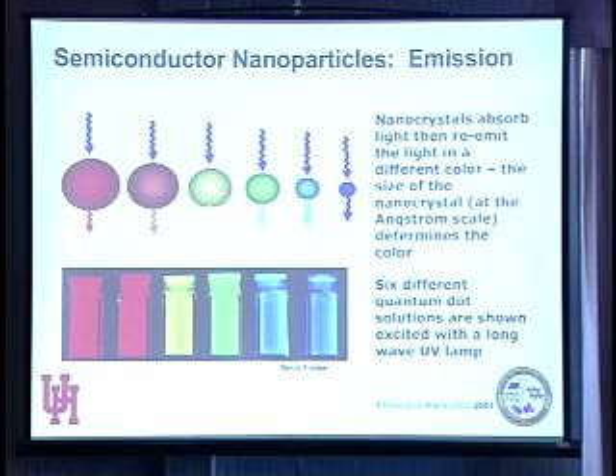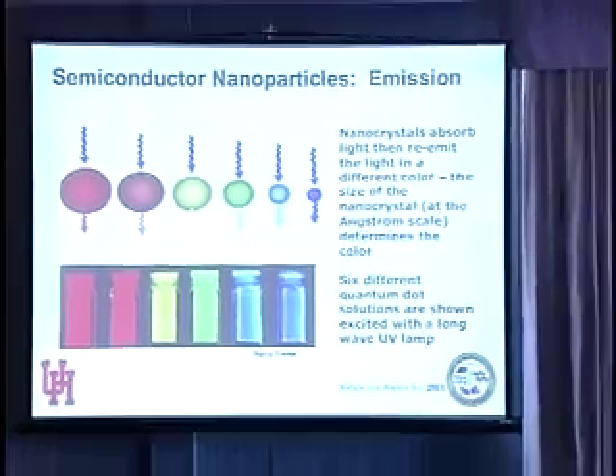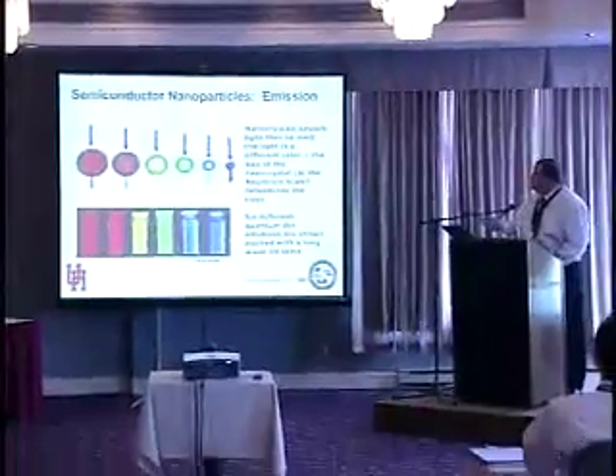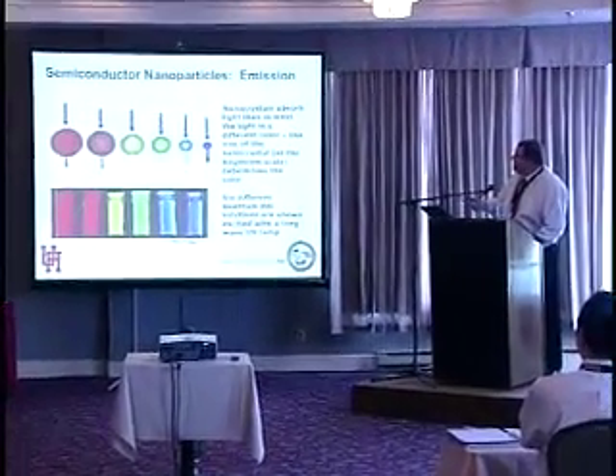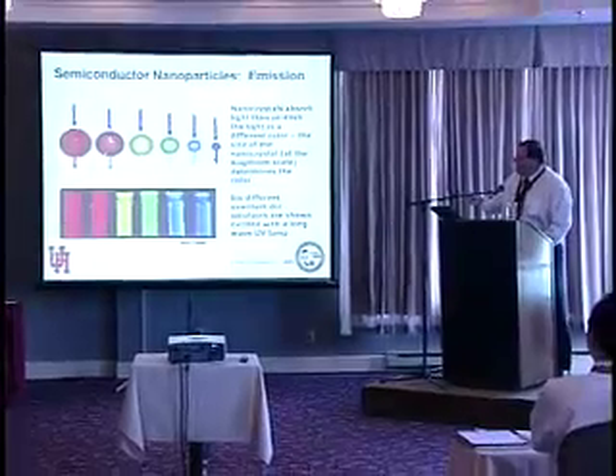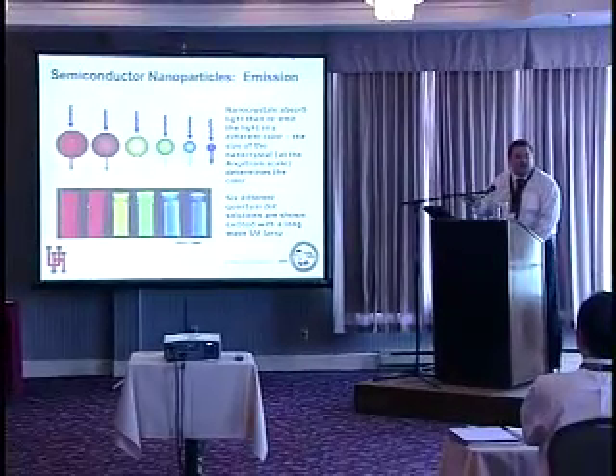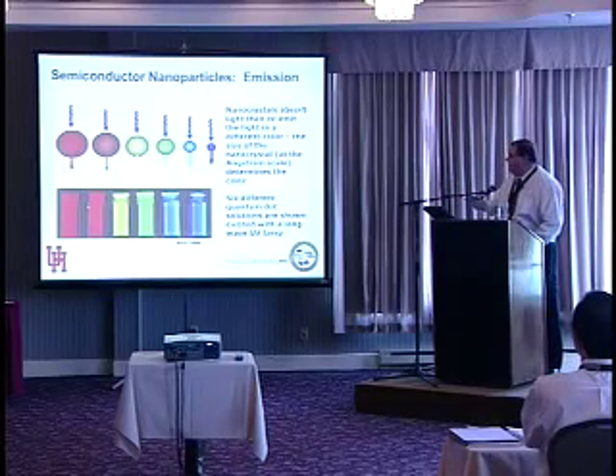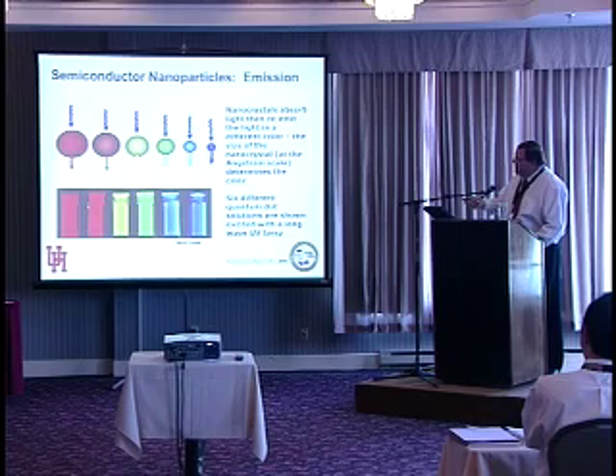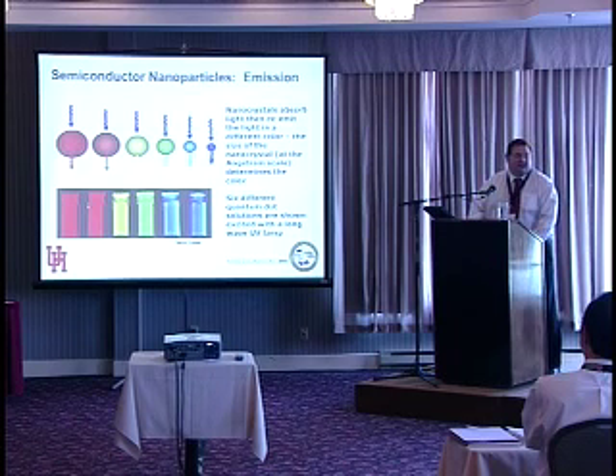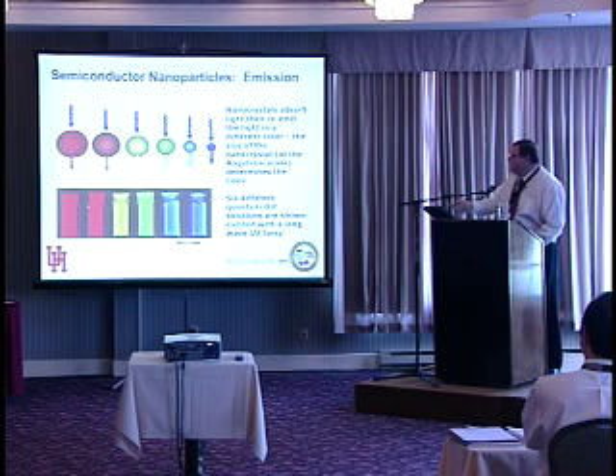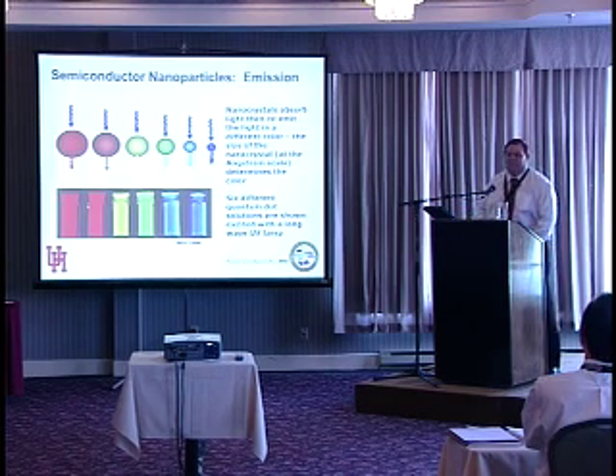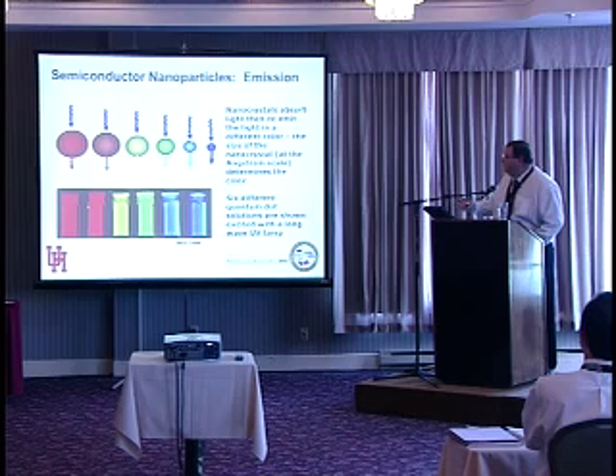Now, I'm sure all of you are familiar with semiconductor nanoparticles. We've actually had some mention of them in the talk so far. And these are really, really interesting materials where one takes a nanoparticle and you can shine light on these nanoparticles. They absorb light and then they re-emit light, okay? And so what's really cool about them is that the wavelength of emission depends on the particle size. So if you're good at doing synthesis, you can manufacture a series of nanoparticles and you can have them emit frequencies, whatever you like, just depending on the particle size. So they're very, very useful and used in a wide range of applications.